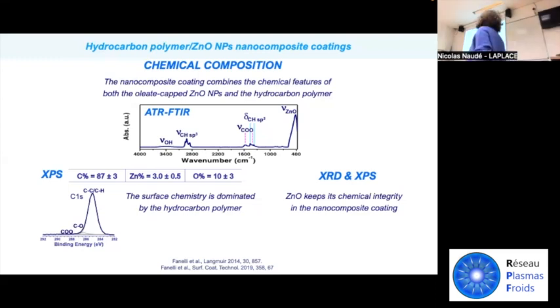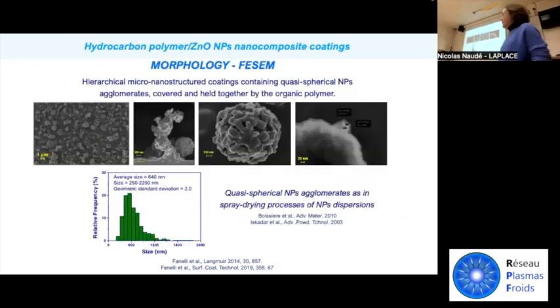What about the zinc oxide nanoparticles? XRD and XPS analysis confirmed that they keep their chemical integrity in the nanocomposite coating. So in principle, we do not change their chemical structure, their composition, and the crystallinity, and so on. Let's move to the morphology.